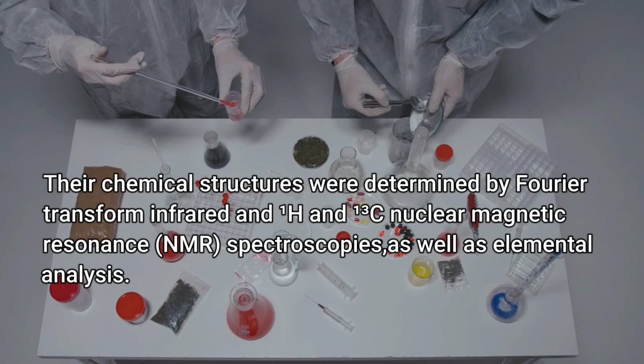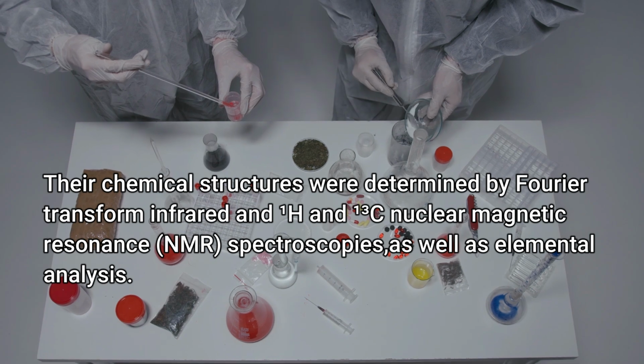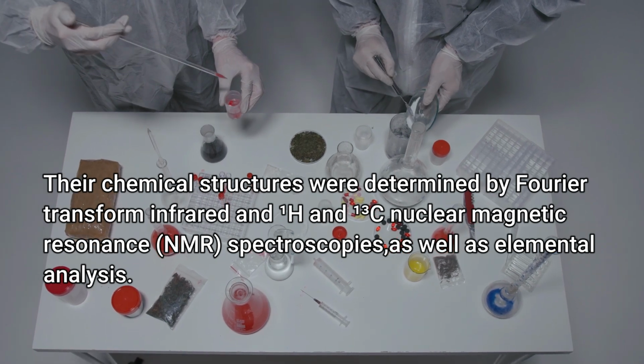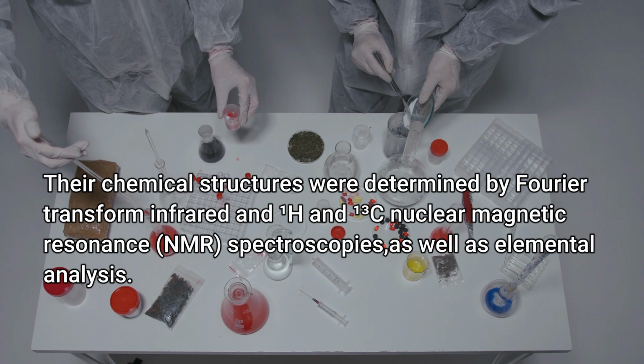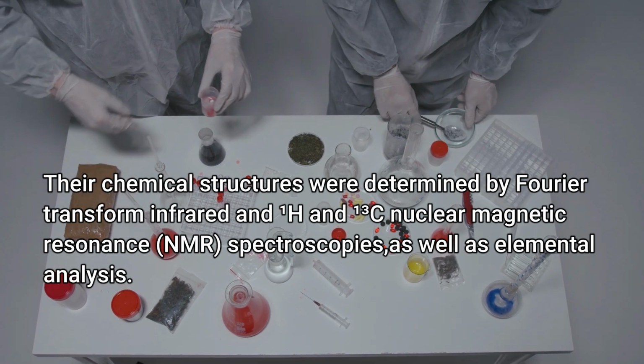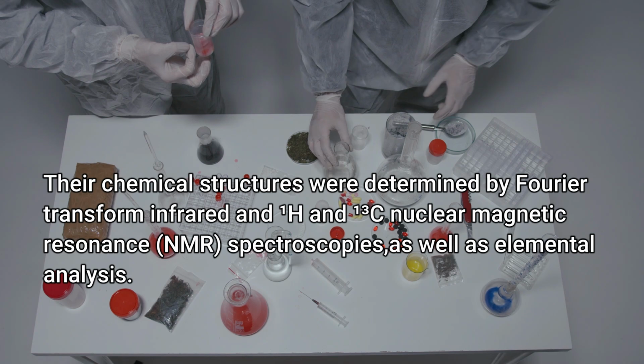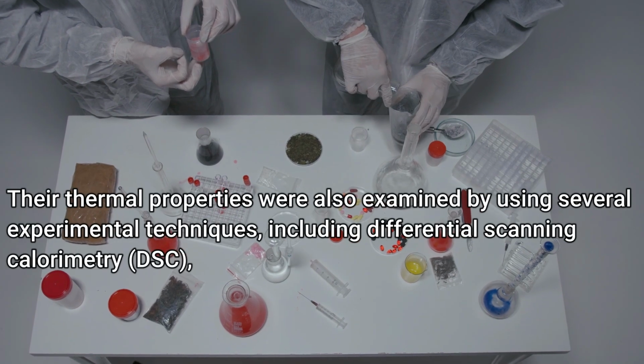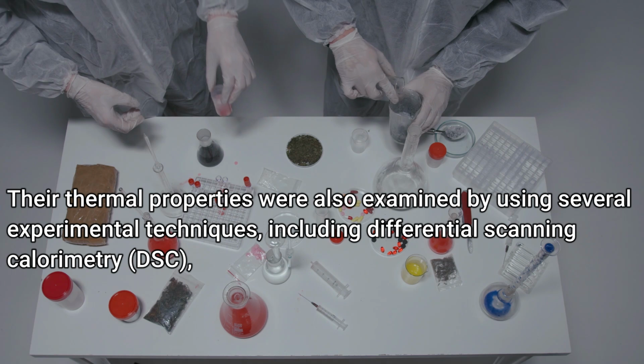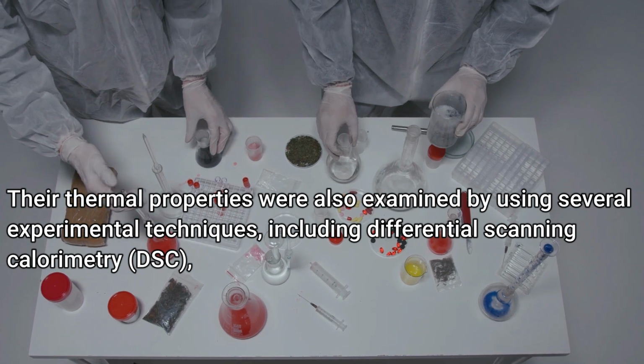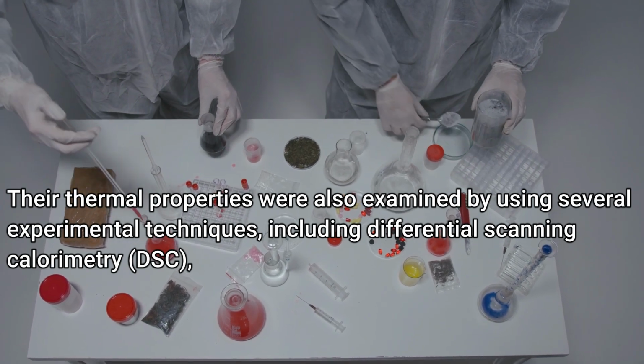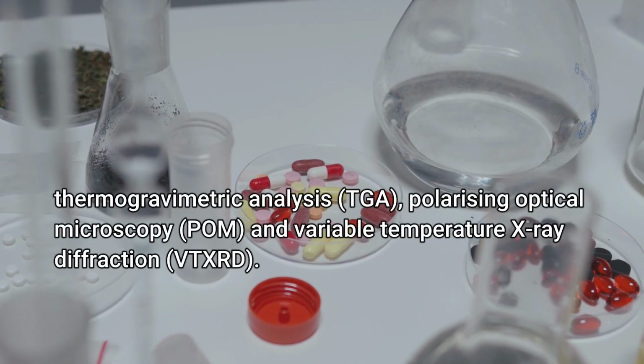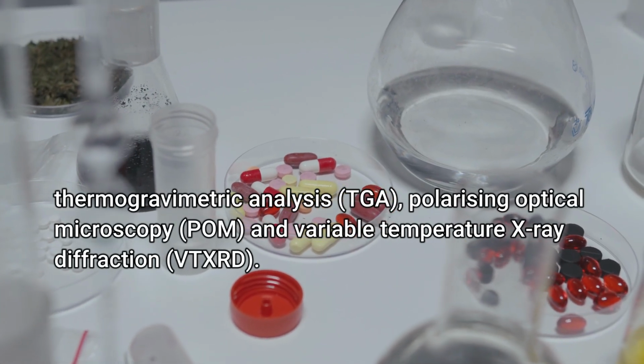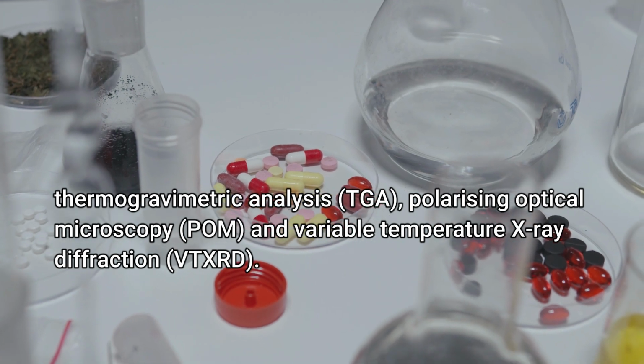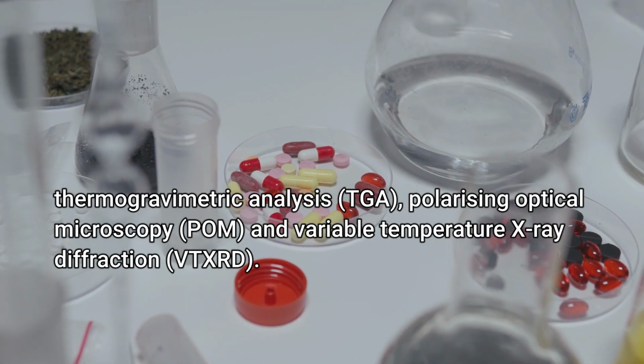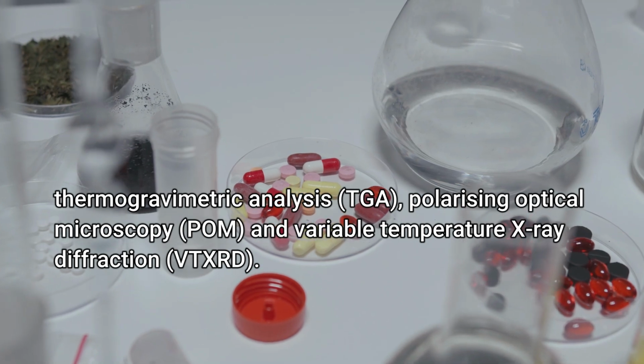described. Their chemical structures were determined by Fourier transform infrared and 1H and 13C nuclear magnetic resonance (NMR) spectroscopies as well as elemental analysis. Their thermal properties were also examined by using several experimental techniques, including differential scanning calorimetry (DSC), thermogravimetric analysis (TGA), polarizing optical microscopy (POM), and variable temperature X-ray diffraction (VT-XRD).